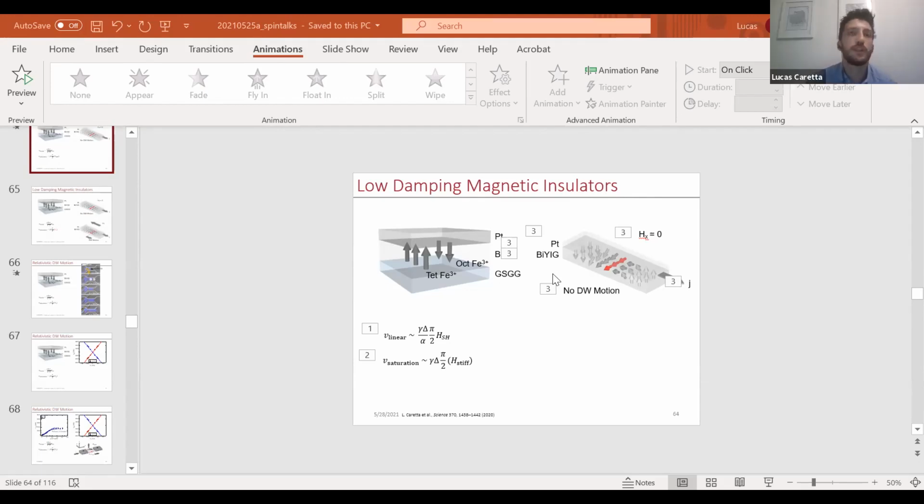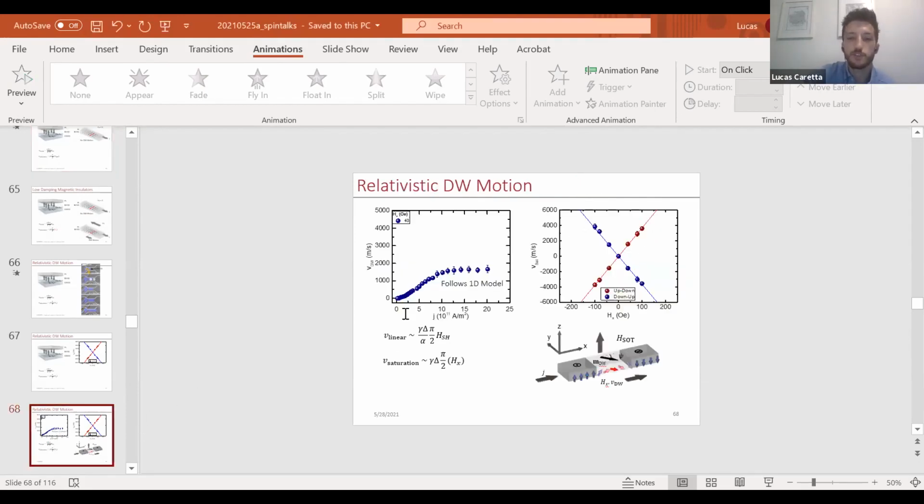Yeah, so this model is a simplified version of that. In this case, what we assume is that the two sublattices have such high, essentially infinite, exchange between them that we can really just represent both of these sublattices by one, which is a net sum of the magnetization and the angular momentum of both of them together. So this is not a two sublattice model. It's actually the limit of the two sublattice model in the high exchange limit. I hope that answers your question.